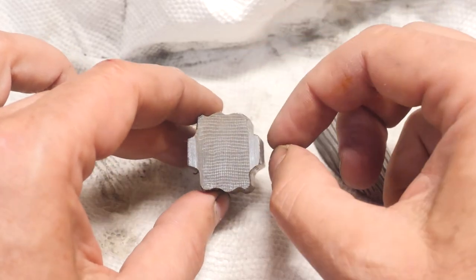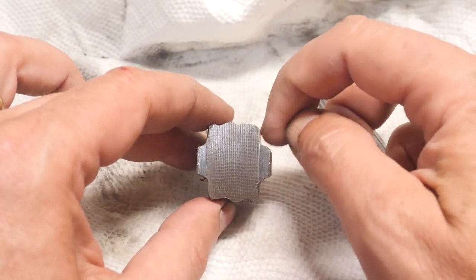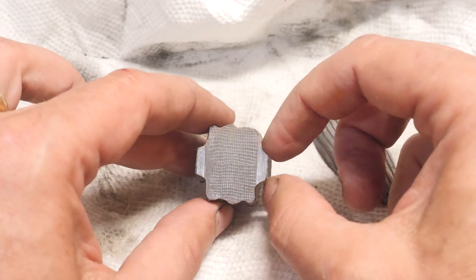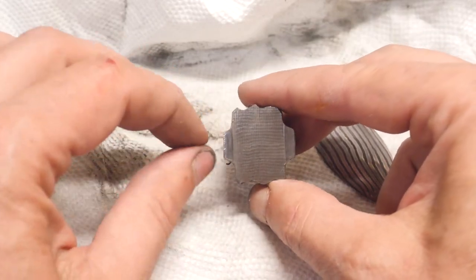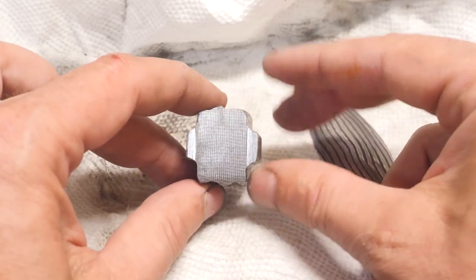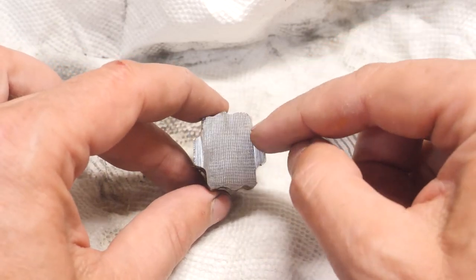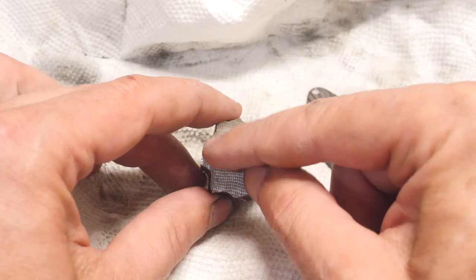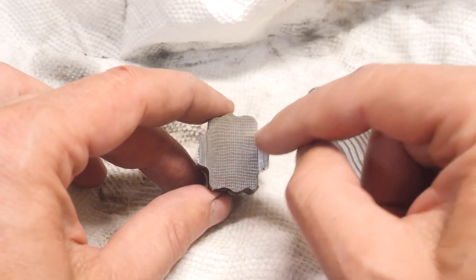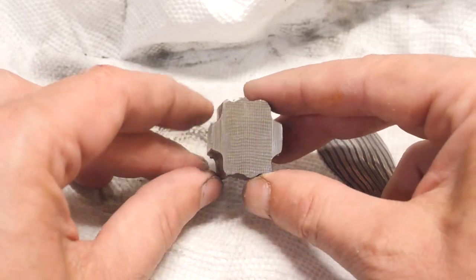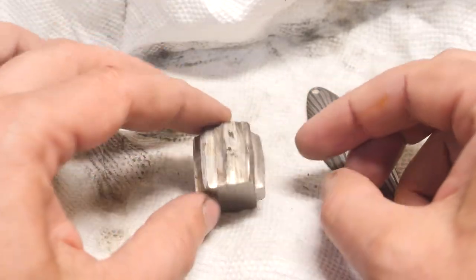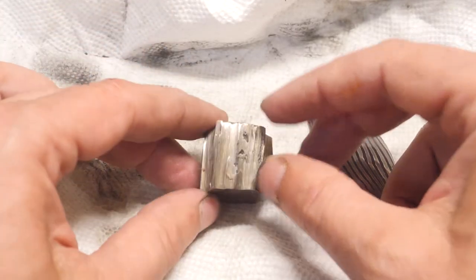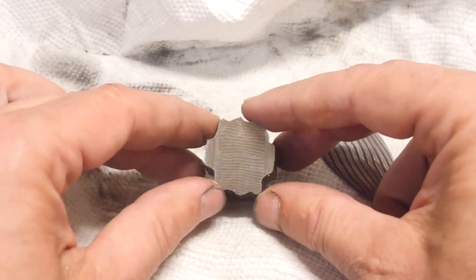The depth here of the stainless pieces is going to be the final depth of the piece, so we won't be compressing the stainless and hopefully we'll keep the stress off these forge welds here between the stainless, nickel, and the rest of the piece. And so it'll squish out this way, and then we'll just grind a bit out of it.